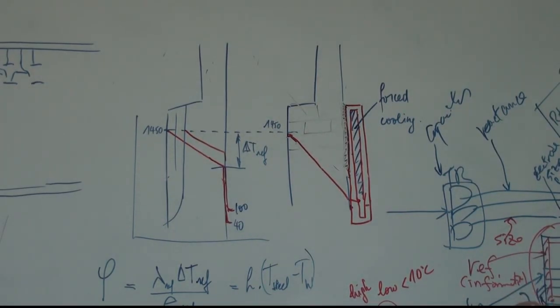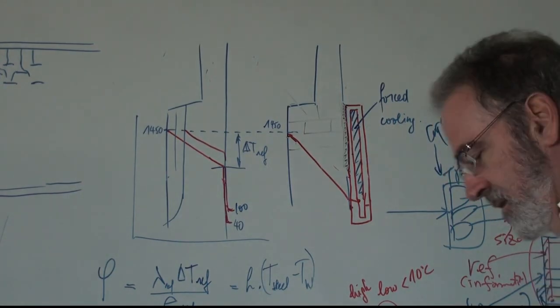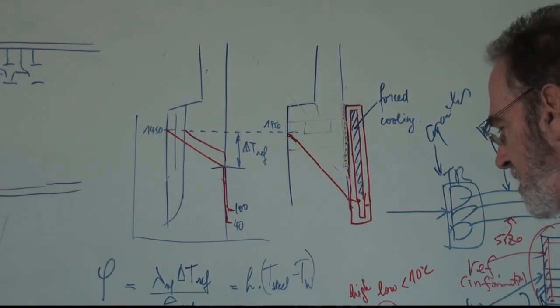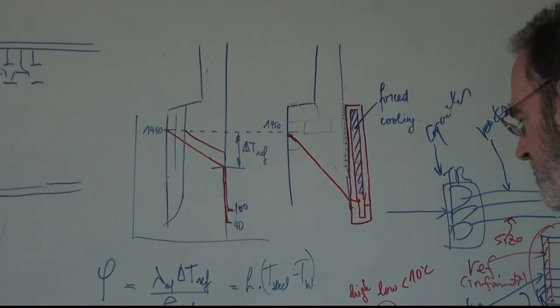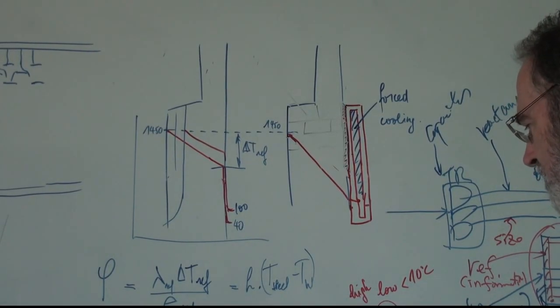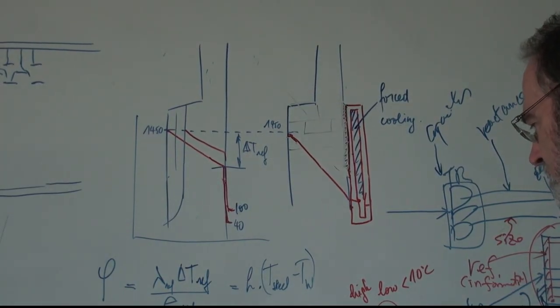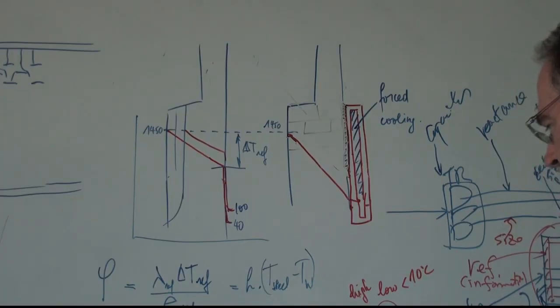But this heat flux must also be equal to H water times T copper minus T water, and this is small, and this must be large, more than 1,000, but maybe a few thousand. What? Watts per square meter per Kelvin.